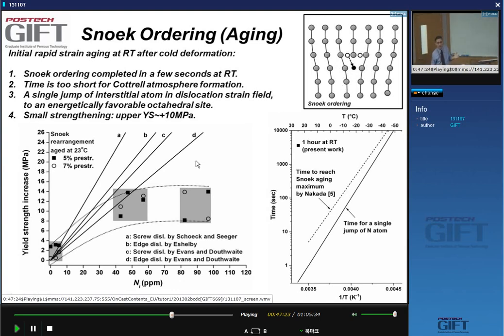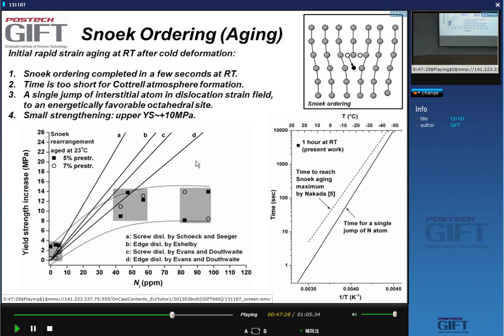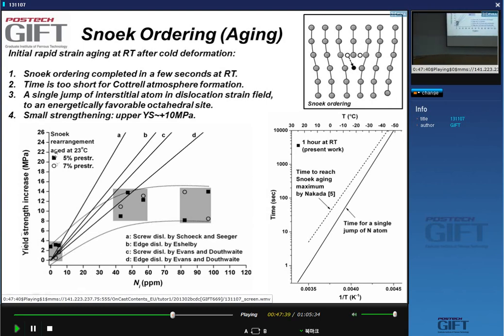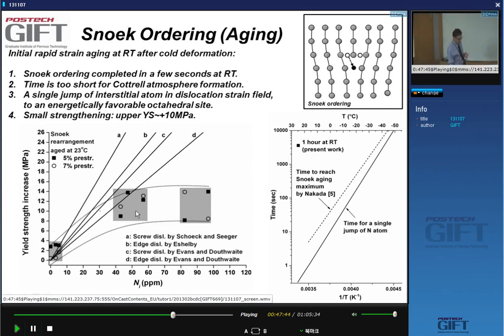Can you rely on Snoek ordering to really strengthen ferritic steels? Not really. The increase in yield strength from interstitial nitrogen via this effect is about 10 MPa — not very much. It can be beneficial in some cases, but it will never give a major increase in strength. In contrast, Cottrell atmosphere formation — where many carbon atoms move toward the dislocation by long-range diffusion upon heating — can achieve 30 to 50 MPa increase in strength, which is more appreciable.